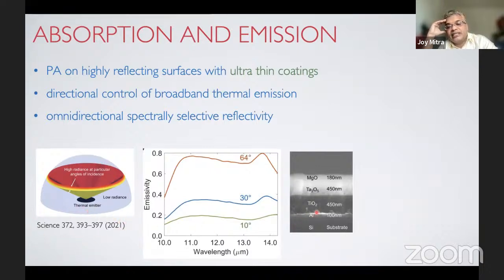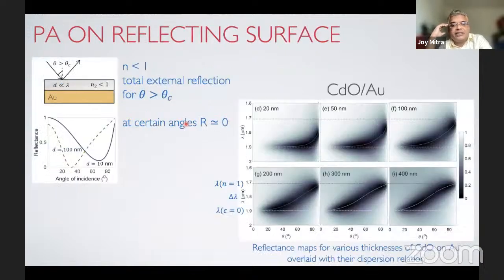It has these oxides, a stack of 3 oxides, and essentially proposes directional control of broadband thermal emission. We, though, have theoretically investigated perfect absorption on highly reflecting materials, and also to some extent omnidirectional spectrally selective reflectivity.